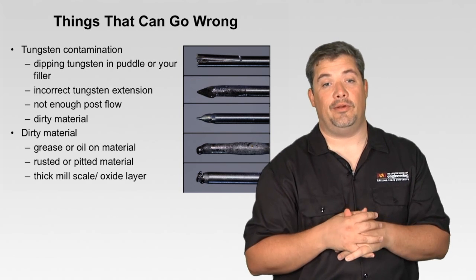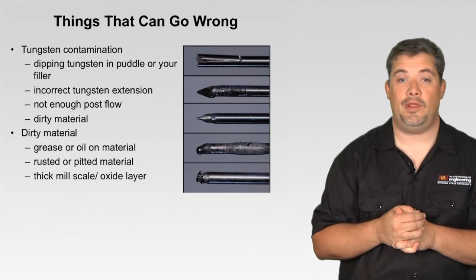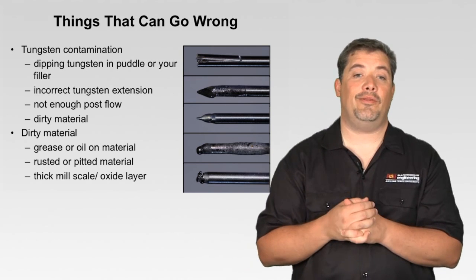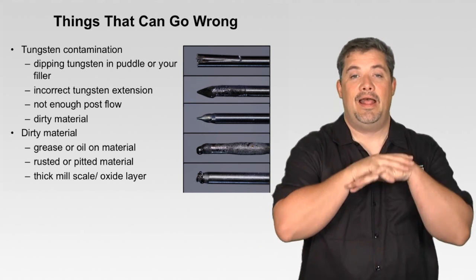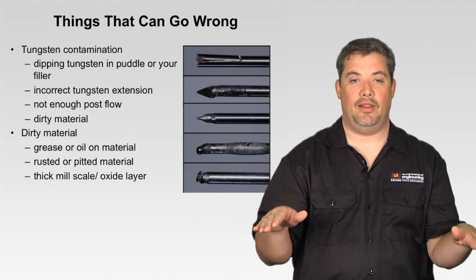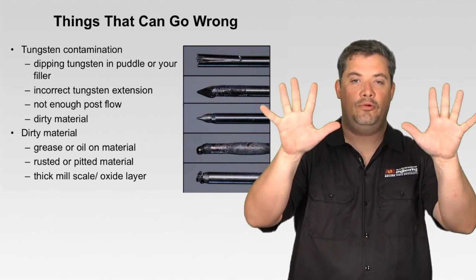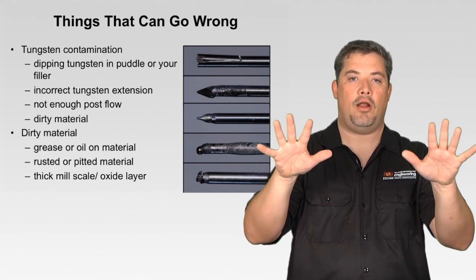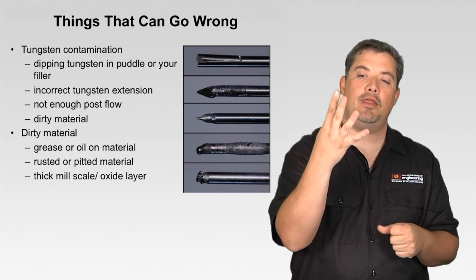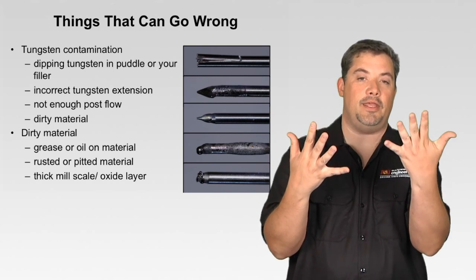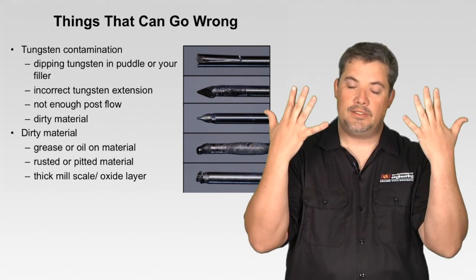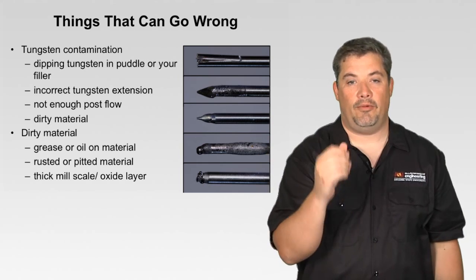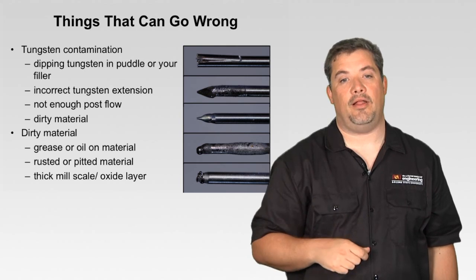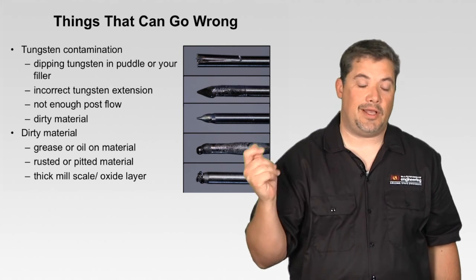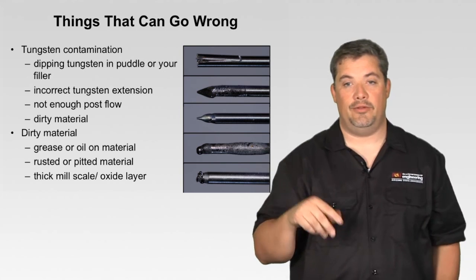And again, dirty material, grease, oil, dust, dirt, debris, rust or pitted material, thick mill scales, oxide layers, they all have to be eliminated off your weld. The first 10 rules to TIG welding are clean, clean, clean, clean, clean, clean, clean, clean, clean, clean. That's the first 10 rules. It's got to be clean. Got to get rid of that mill scale. We need to sand that mill scale off. Any rust, got to get rid of that rust. And oil, bad news no matter what.